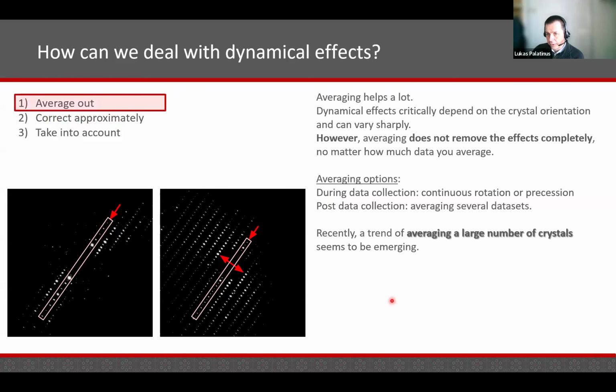So when talking about averaging, averaging helps a lot when it comes to suppressing the dynamical diffraction effects, because the effects depend critically on crystal orientation and they can vary sharply. So if you average the diffracted intensities over many crystal orientations, there is a chance to smooth out or average out the dynamical effects. That works reasonably well, but it's important to keep in mind that this approach does not remove the effects completely, no matter how much data you average.